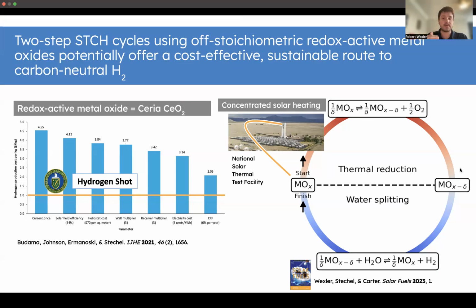Again, these are conditions that we've chosen. And then it's exposed to steam, and that leads to reoxidation of the metal oxide, not always to its original stoichiometric form. And this oxidation removes oxygen from water and produces hydrogen gas.